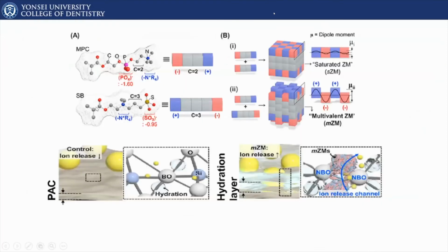Then we went further to try to find out what the basic mechanism behind it might be. We found out that MPC and SB have different lateral polarity, as you can see here, in the molecular lengths or the overall polar end of these molecules. When we have similar molecules, so when we have just MPC without any SB on it, for example SZM, this will result in a saturated form of dipole moment. But when we have a mixture of these two, as you can see here, there's a disparity of this polar nature, and it causes multivalent zwitterionic materials.